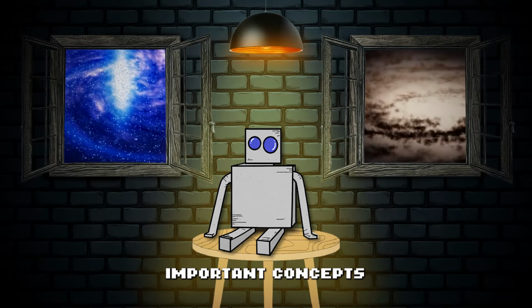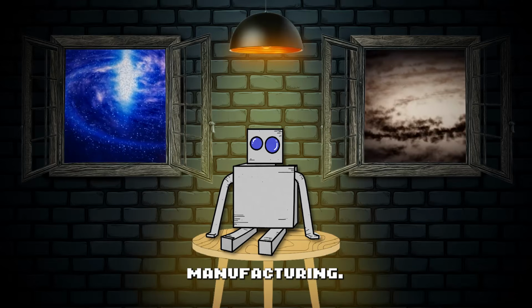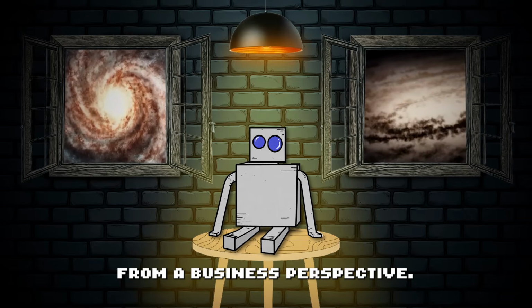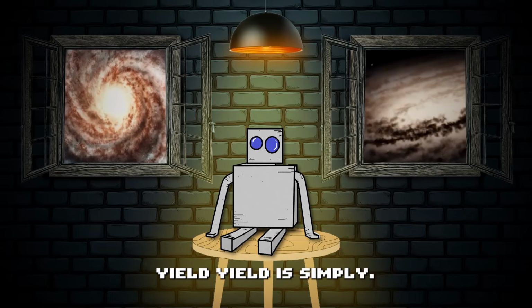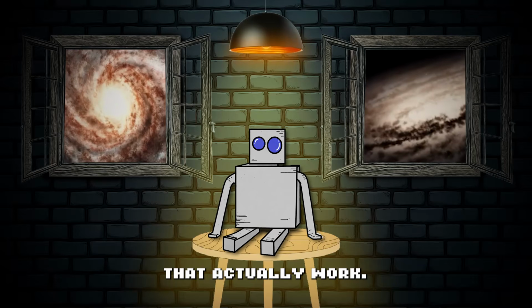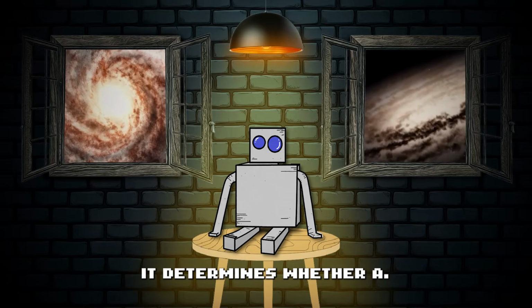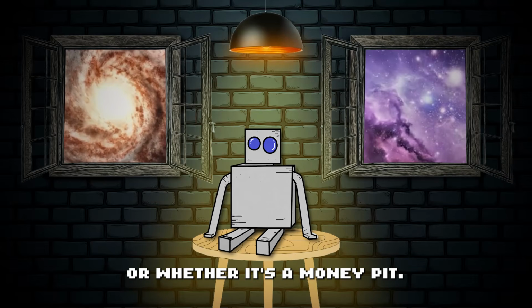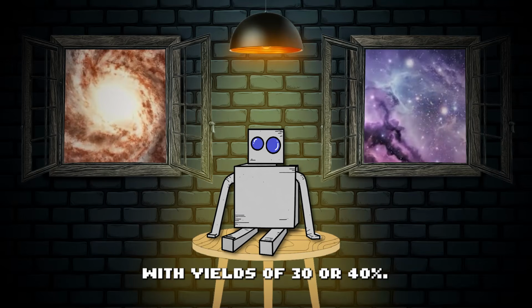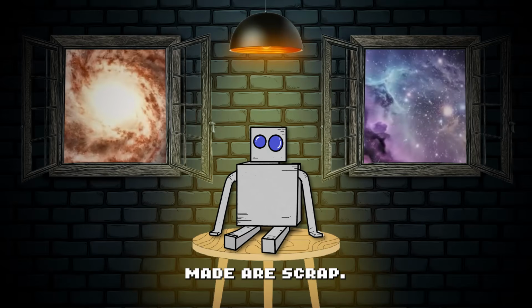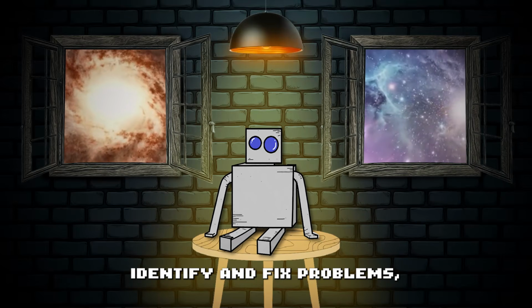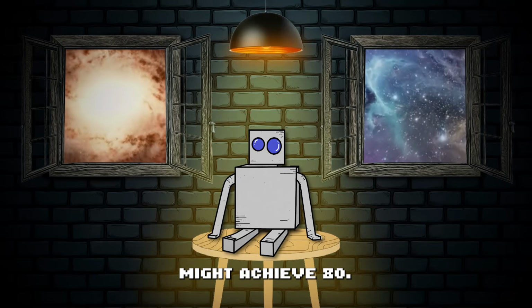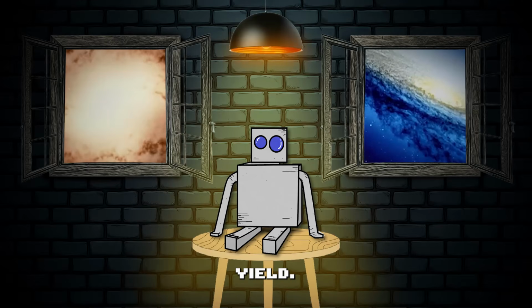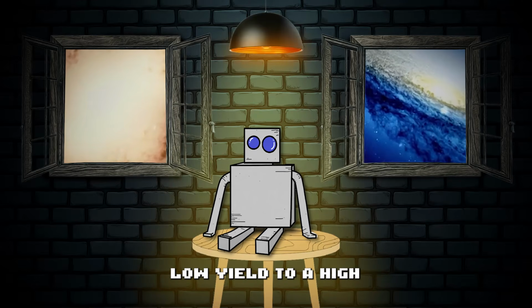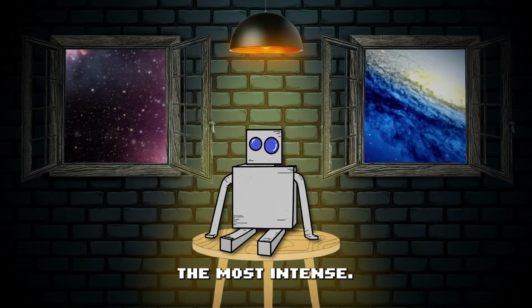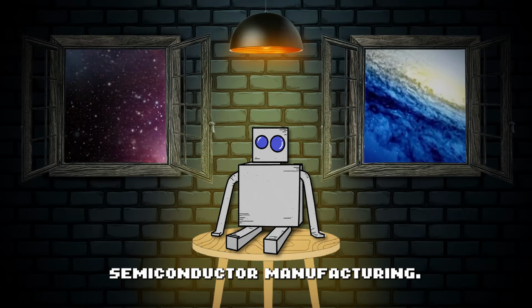This brings us to one of the most important concepts in semiconductor manufacturing, and honestly one of the most fascinating from a business perspective: yield. Yield is simply the percentage of dies on a wafer that actually work. And yield is everything. It determines whether a chip is profitable or whether it's a money pit. A new process might start with yields of 30 or 40%, meaning more than half the dies you made are scrap. As engineers identify and fix problems, yields climb. A mature process might achieve 80, 85, even 90% yield. Getting from that initial low yield to a high stable yield is called yield ramp, and it's one of the most intense, high-pressure phases in semiconductor manufacturing.